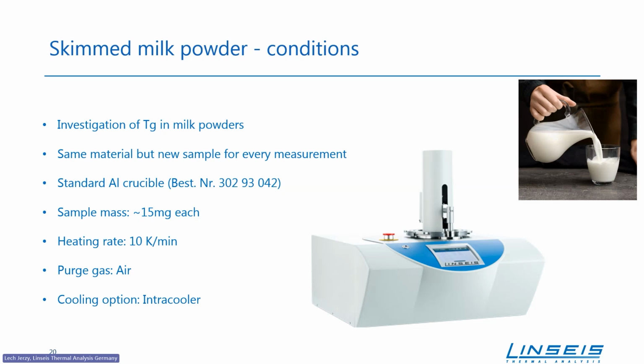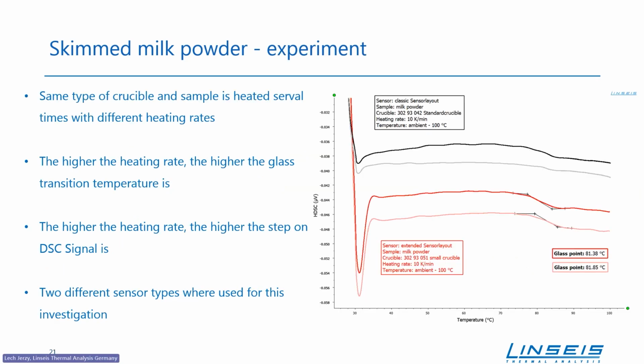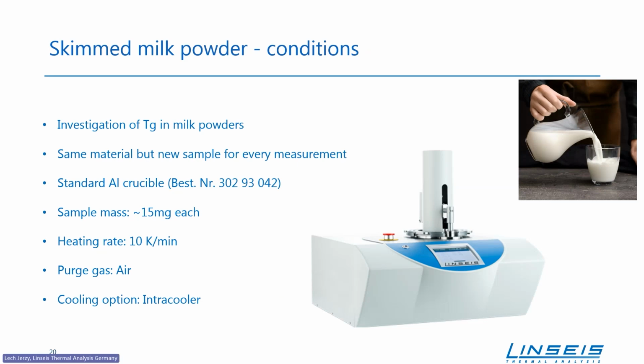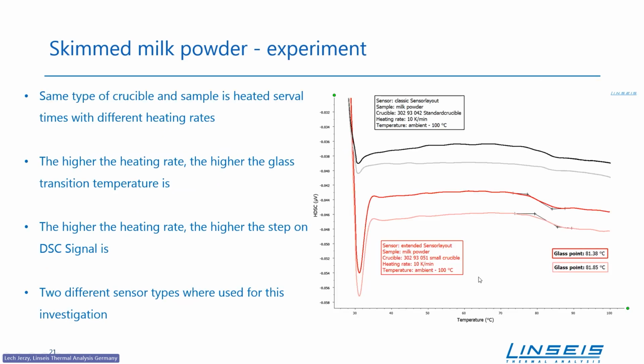We used these conditions for this measurement. In this case we have skimmed milk powder, which consists of more than 50% lactose. As you can see, it shows the glass transition at about 81 Celsius. We use the same type of crucible and the sample was heated several times with different heating rates, in this case 10 Kelvin per minute. The result depended on heating rate: the higher the heating rate, the higher the glass transition temperature is.